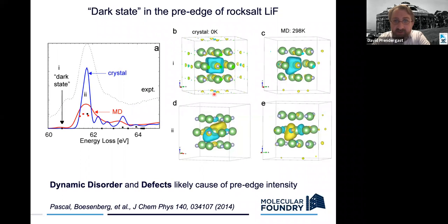It turns out that if you model the crystal with no perturbations, so let's say not really 0 Kelvin, but with no zero-point motion either, the atoms are clamped in place and they don't move, you'll see that the very first excitation, this blue box around the lithium atom in its center, definitely doesn't have any P character. It's inversion symmetric. And so there is a dark state that defines that excitation. If you do the simulation, you'll see that it doesn't have any intensity in the X-ray absorption.